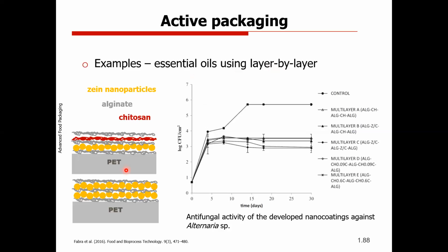So what we did was to put PET, alginate, zein nanoparticles, alginate, zein nanoparticles, alginate. So we have here our essential oil in zein nanoparticles, and in the other, we try to use alginate, zein nanoparticles, alginate, chitosan, and alginate. And then we go through some tests.